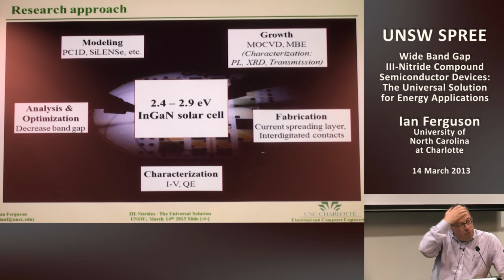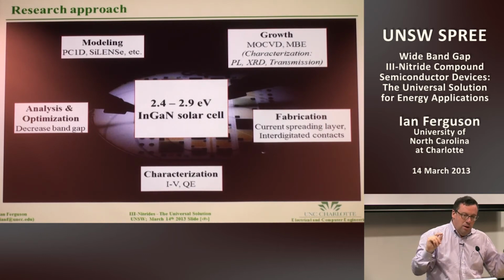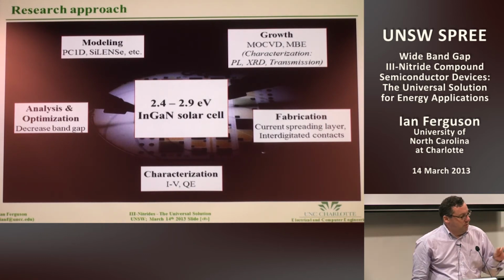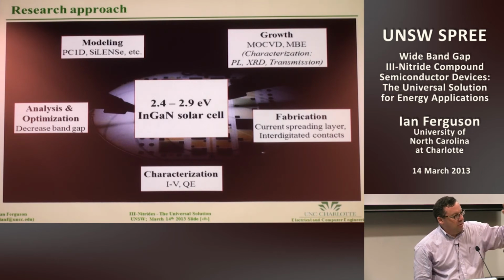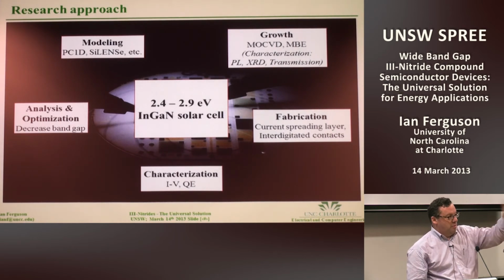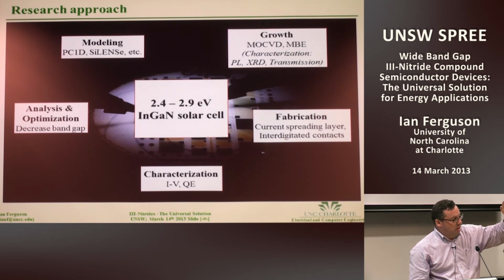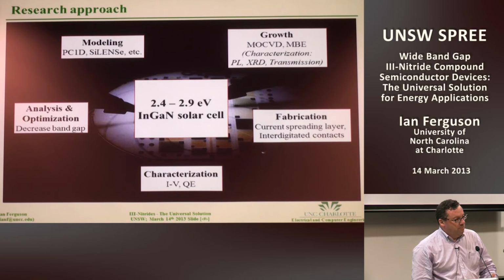The other issue with the nitrides is that they're actually hexagonal materials. That means hexagonal semiconductors are non-central symmetric, if you know crystal theory. When it's non-central symmetric, you're going to see spontaneous polarization effects depending on the differences in materials you put on. And if there's strain, those can create quite large fields and redistribution of carriers. When you have strains, you can also get polarization effects as well.